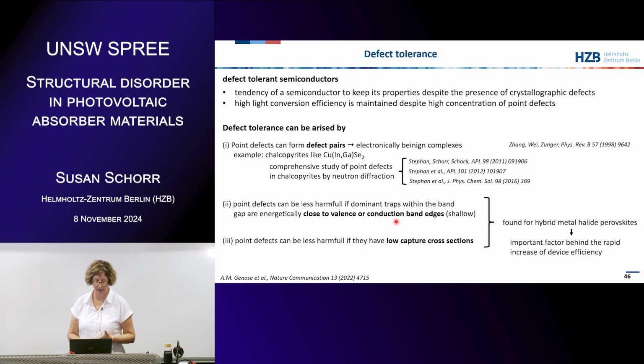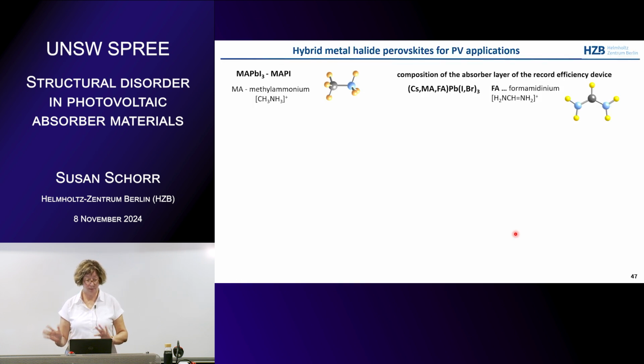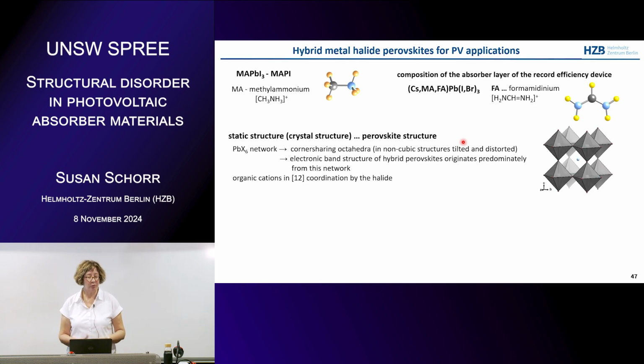Second, of course, the point defects can be shallow. You only have shallow point defects, or you have point defects which are deep, but they have a low capture cross-section. And these two points are found valid for hybrid halide perovskites. And that's why, despite the fact that they may have a lot of point defects, they are not bad for the material. So hybrid metal halide perovskites, you know, you have these molecules in the material, methylammonium or formamidinium, for instance. What was mostly studied is methylammonium lead iodide, so MAPI. This is the composition of the record solar cell. It's cesium, methylammonium, formamidinium, lead, iodide, bromide. So it's a mixture of cations and anions.